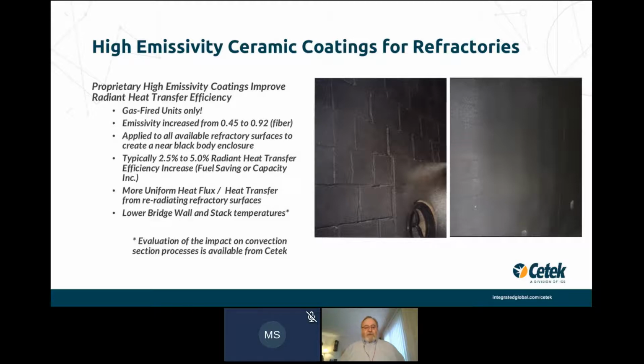unit. Because we're making the heat exchange more efficient, we tend to end up with lower bridge wall temperatures and lower stack temperatures. And sometimes that can lead to problems, especially if you're using the convection section for process preheat or steam production. In a steam methane reformer, we have to be very careful. So you can see at the bottom there, an evaluation of the impact on the convection section is very important. And that's why we like to do an evaluation before we undertake any application that we make.